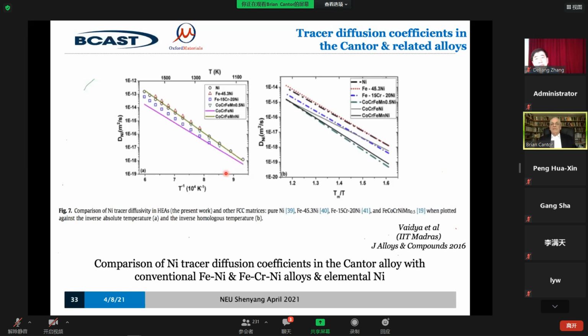People pointed out that it isn't simply related to the number of components. The more components you have, the more likely it is that diffusion will be difficult, but it depends which components are. If you have manganese in the material, because of its larger size and its higher enthalpy of mixing, it slows down the diffusion more than if you have some other elements in there. So that's the diffusion effect.